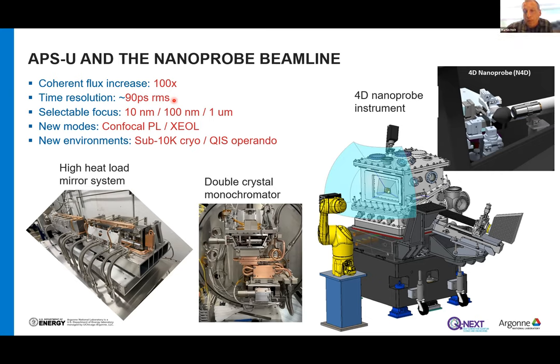So our approach now, and we do actually modify with the beam about 50% of the types of samples we look at, and I feel that'll go up to most of them, is that you have to self-consistently understand the rate of change of your sample. And I don't mean damage, because it is a chemical activity more than heat or charging. Your oxide films in particular have high oxygen mobility. These silicon germanium structures that don't have a barrier oxide layer are very resilient, but things near oxygen now have this nice tunnel to hop the oxygen through. So how do you mitigate that? Or what kind of capping layers that we didn't need to think about before can help?